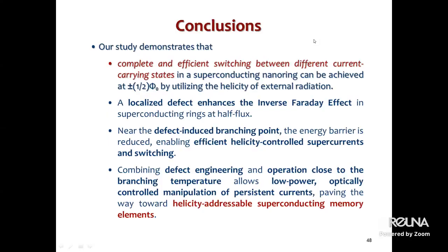But as I said, the next step will of course be to include random defects, with correlation or without correlation, but that is already a second question, and to study what will happen then. Here one has to take into account that if we have many defects, a disorder whose strength is not strong, then we can renormalize our parameters like coherence length, London penetration depth, and the rest, and make the system inhomogeneous. The only important thing is going to very strong disorder. But when it is very strong disorder, then we can kill superconductivity altogether.